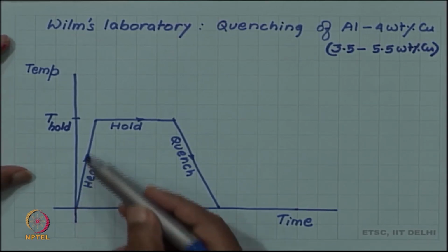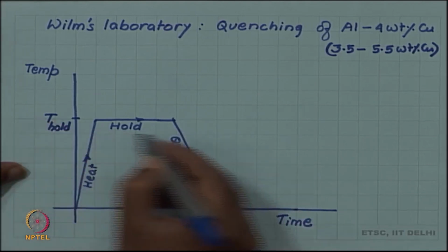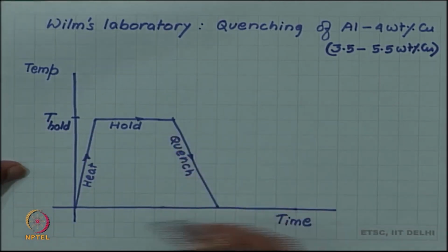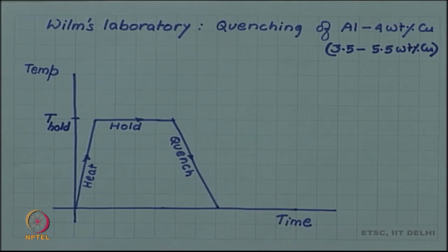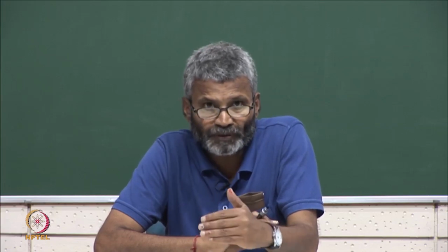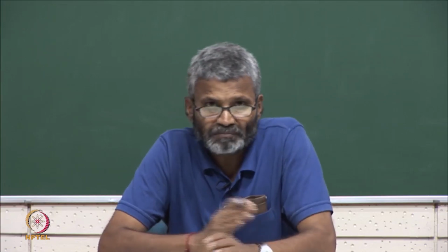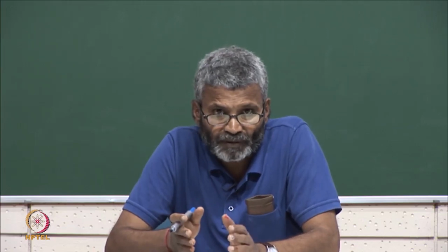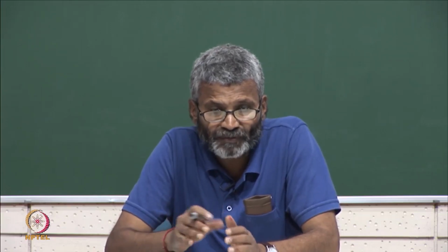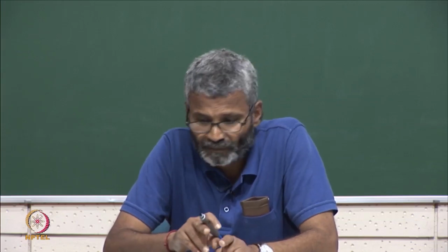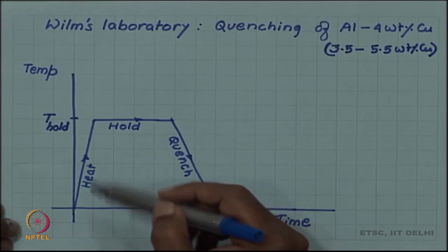He had several variables in his hand. At what temperature do you hold and at what rate do you quench? We know from the steel example that if we do not go to the temperature range in which the austenite phase is stable, and we take it only below the eutectoid temperature and then quench, it is not going to have an effect. You will not have austenite to begin with, and there will be no martensite forming. So, if you want to form martensite, you have to heat it above the austenite temperature.